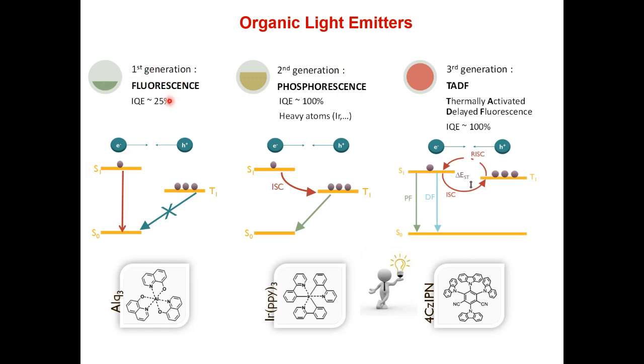Another thing is that for most of the fluorescent molecules, quantum mechanics teaches us that when you have recombination, you will make 3/4 of triplet and only 1/4 of singlet. But the bad news is that all the triplet excitations cannot recombine radiatively, because for light molecules with carbon and hydrogen, you would need to reverse the spin to go back to the singlet ground state. And this is very slow and mostly forbidden for many, many small molecules. And so you lose automatically 75% of the charges that have recombined. It's bad news. And this puts the limit of the efficiency at 25%.